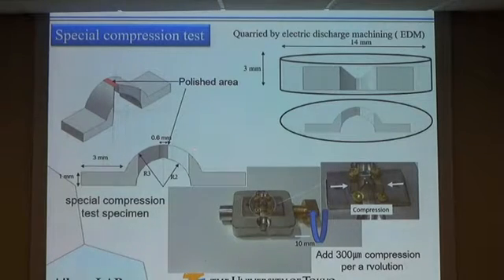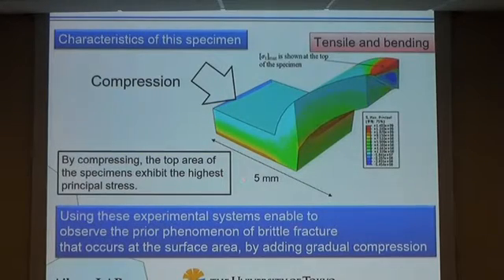Okay, then we designed special compression test specimens like this. Here, the top surface of this specimen is polished and will be observed. And we can add compression loading by this jig. We can add 300 micrometer compression per revolution of this screw. This specimen has very good characteristics for in situ observation of brittle fracture. Because, as shown in this figure, by compressing the specimen, the top area exhibits the highest principal stress. So, using this specimen, we can observe the precursor phenomenon of brittle fracture that occurs at the surface area by adding gradual compression.